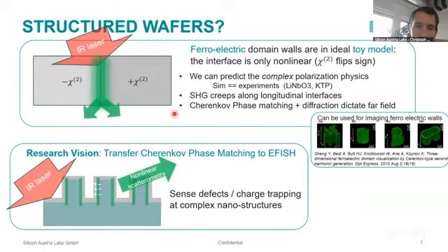In any case, what we then want to do is to apply the so-called Cherenkov phase matching condition to basically E-fish. So let's say you have a structured wafer, and then you have like side walls here. And on these side walls, it's also very critical to understand defects or the interface quality there. So when you have a space charge region due to trapping of charges at the side wall, we want to find the right polarization, wavelengths, and wave vector configuration to basically enable the same mechanism that happens at these ferroelectric domain walls. And therefore, we hope to be eventually able to make a phase matching along the side walls, and therefore generate very strong second harmonic signals depending on the defect situation and the local charges at the side walls, to then be able to detect defects at such complex nanostructures.